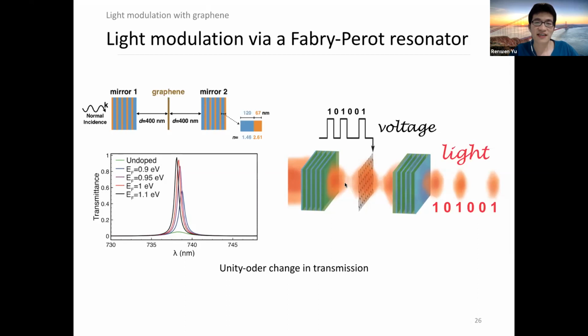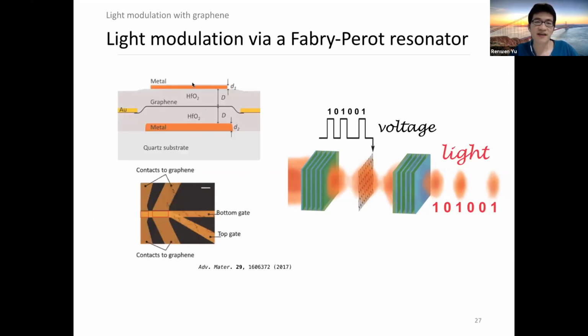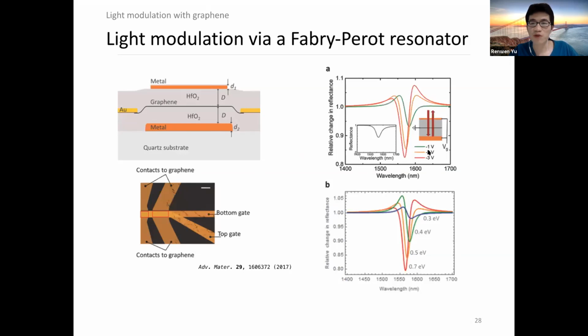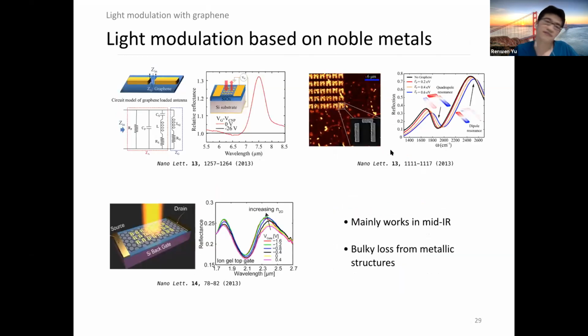People have followed this idea, and they have built a Fabry-Perot cavity. Instead of two Bragg mirrors, they are using two metallic films as two metal mirrors, and they have achieved a modulation depth in reflection of around 20% in their experimental study. Besides using this Fabry-Perot cavity, one can also think about other means. For example, one can integrate graphene with metal-based structures. People have been thinking about this method in the mid-infrared wavelength range, but due to the bulk losses from the metallic structures in the mid-infrared wavelength range, the modulation depths are very small, as you can see here.